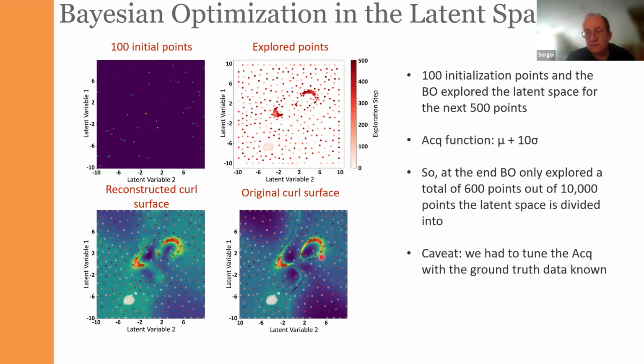And remember the primary consideration about the simple Gaussian process, that we have a single kernel. The length scale of the kernel represents the length scale at which the properties change. So the Bayesian optimization doesn't trust the properties if they're further away than the kernel length. As you can see on the ground truth data, the size of these features is relatively small, and they also have kind of any which orientation in the latent space, which basically means that the kernel length is also very small. If the kernel length here is small, that means that the algorithm has to explore the whole latent space in such a way that the distance between the sample points does not exceed the kernel length scale, which in turn is related to the scale of these features.